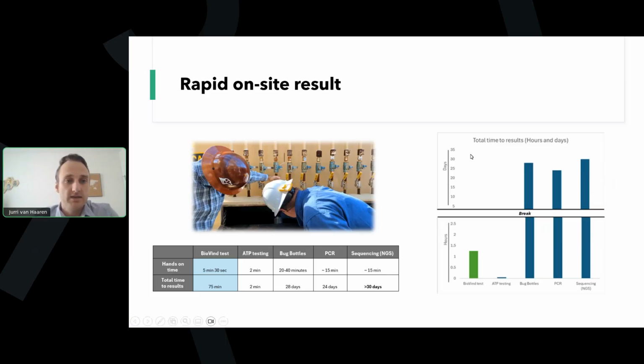Something else we tested while we were on site was usability of the BioVind test. We measured the total hands-on time as well as the total time to results when using these tests. We found that with the BioVind test, you have a total hands-on time of about 5 minutes and 30 seconds and a total time to results of about 75 minutes.